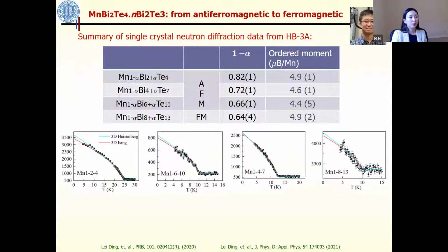And then Hui Bo from Oak Ridge National Lab did single crystal neutron diffraction measurement. So he was able to figure out the crystal structure of the 1-8-13, which was never discovered before, and therefore there was no crystal structure information. And he also was able to find that there was actually manganese deficiency on the manganese site. So you can see for the pure 124, you have 18% of deficiency on the manganese site. And once you go to even higher N number, the deficiency, the vacancy increases from 18 up to 36.